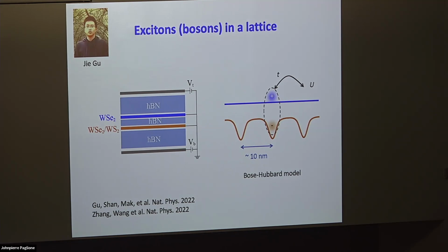So just a quick question, when you say graphite gate, does that mean you actually mount a piece of graphite on top? It's a few-layer graphene, so it's still very thin. It's the same process, the same graphene. Then you would pick up the graphene first, and you pick up the rest. How many layers? Five layers? Yeah, typically a few layers, on the order of 3 nanometers. No, 3 nanometers, 10 layers. I would say 2 nanometer-ish.